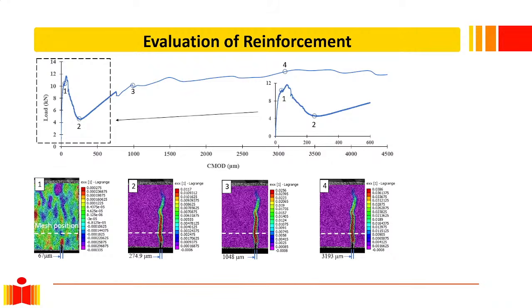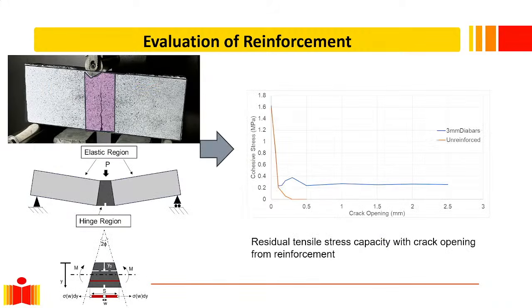If you look at the load response of this beam tested in fracture, the load builds up to a high value, a crack forms, you can see the progression of the crack, and then the steel eventually does catch up. So the steel starts giving a response. Mind you, this is just a 3 millimeter steel wire that's simply placed between the two layers, and I'm able to get some residual force transfer from this concrete by just simply placing the steel between the layers. And we can actually do some fracture analysis, and from here we can extract what is called the cohesive stress.